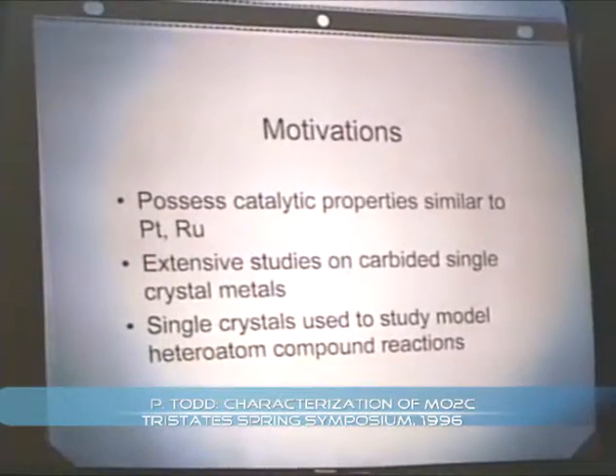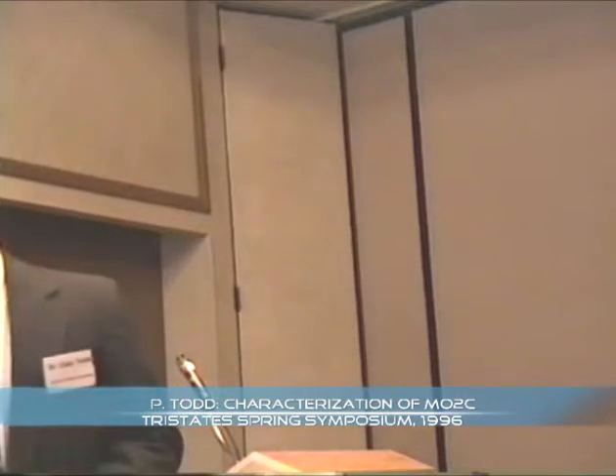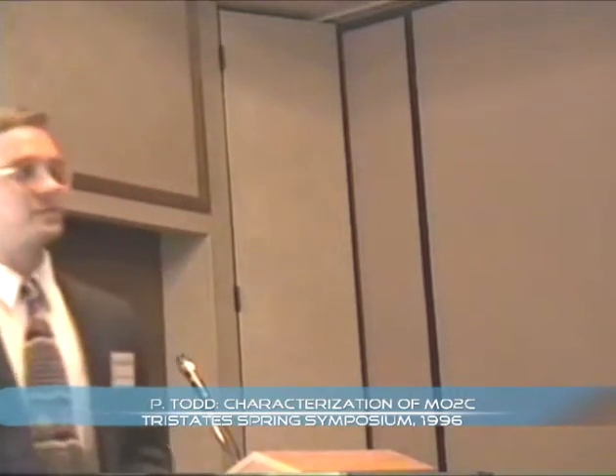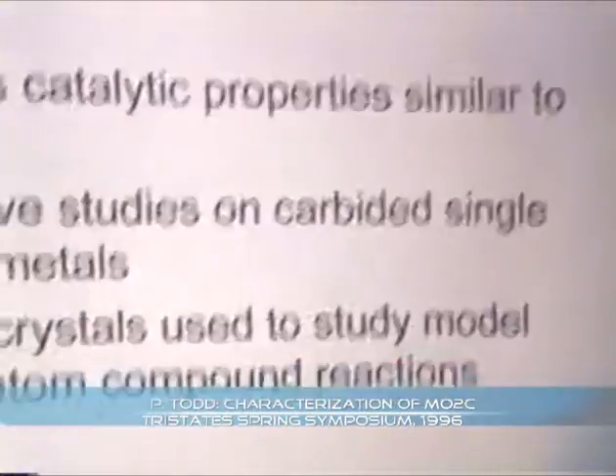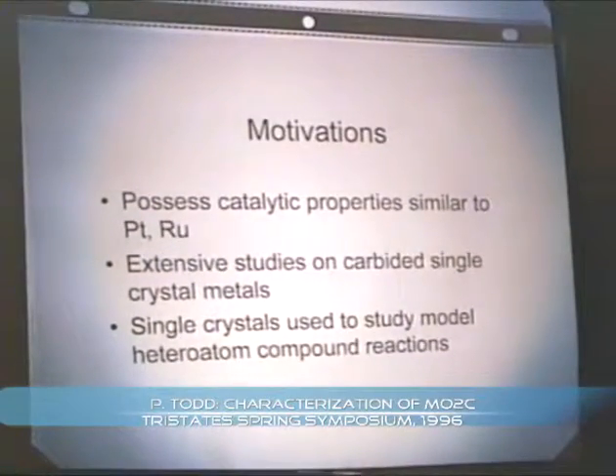The transition metal carbides and nitrides are well known to possess catalytic properties that are similar to that of platinum and ruthenium. This was first demonstrated in 1973 by Levy and Boudart, who reported the selectivity of a tungsten carbide catalyst was comparable to that of platinum for the isomerization reaction of neopentane. This sparked a flurry of interest in the carbides and nitrides as possible inexpensive alternatives to the more expensive noble metal catalysts widely used in industry.